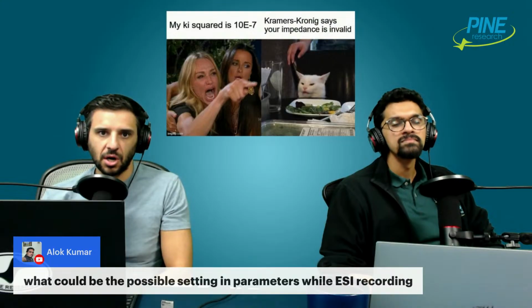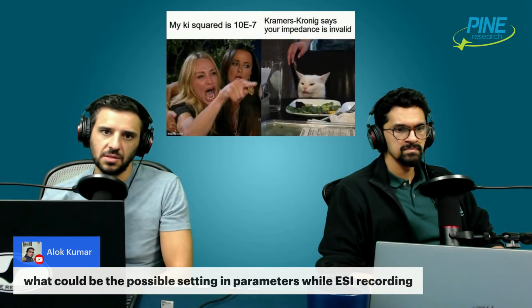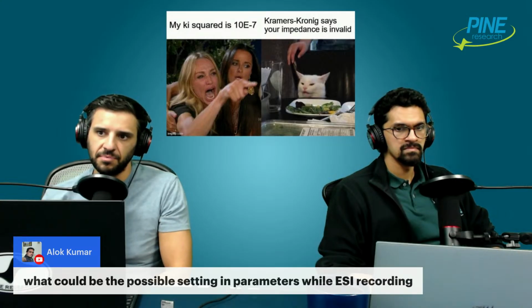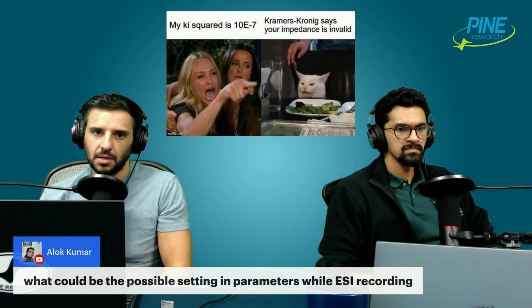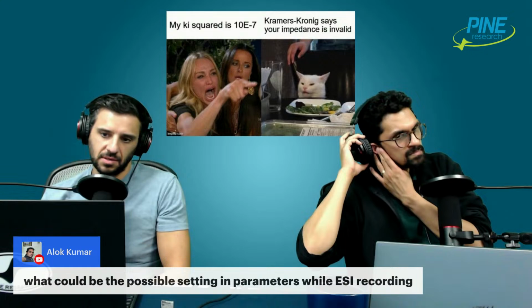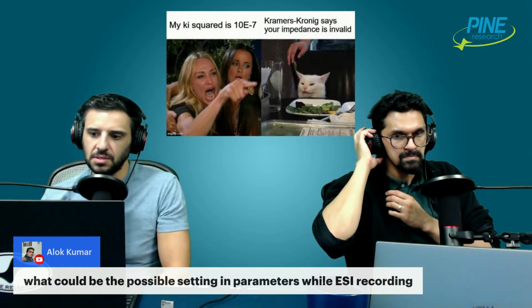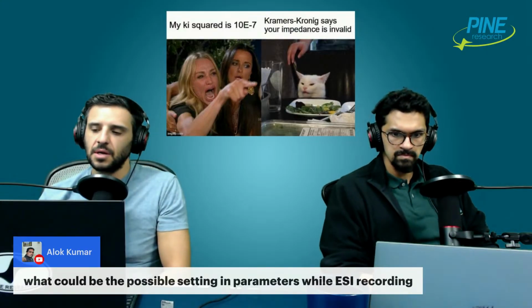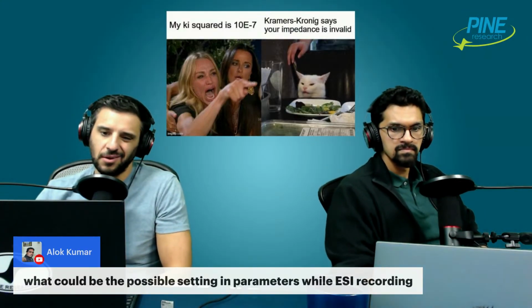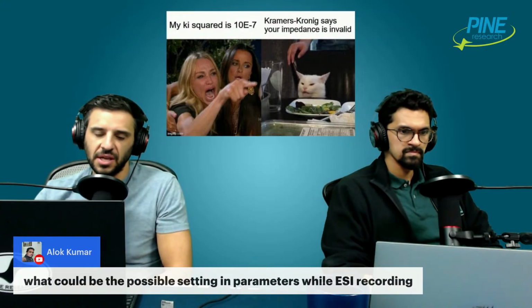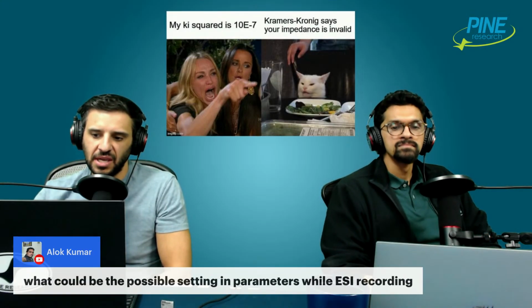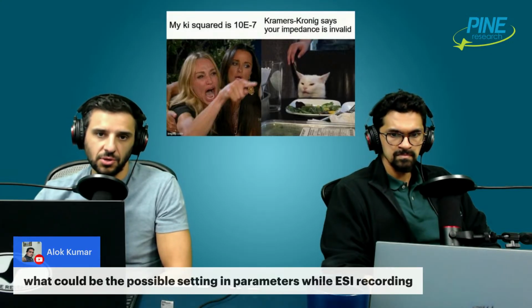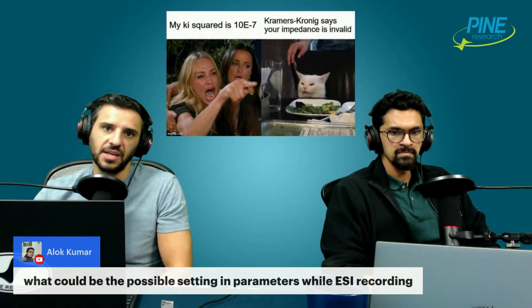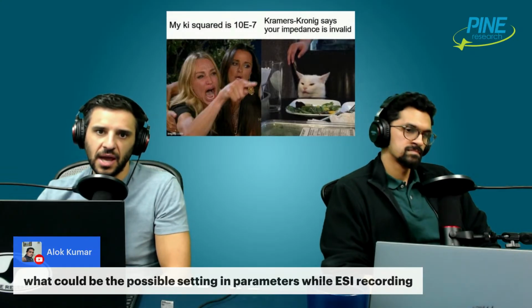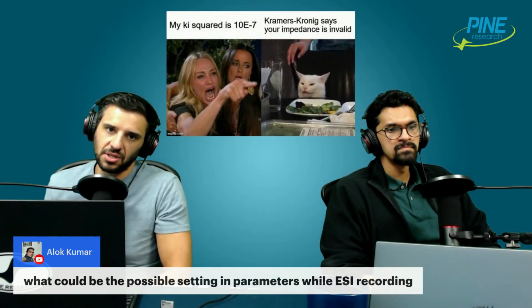Most commonly, you're going to start at 1 megahertz to 100 kilohertz as the upper range. A lot of software and potentiostats can go up to about a megahertz, but there's usually not a lot of information in a lot of systems above 100 kilohertz. But you're not going to hurt anything by doing a megahertz, so you could start there if you want. The highest frequency decade is probably irrelevant, but that's okay. You can ignore those data later. I usually have my lower limit be about 0.1 hertz. 100 millihertz is usually the lowest limit I can tolerate. It takes a long time if you go lower than that. And anywhere from 6 to 10 points per decade is usually good.